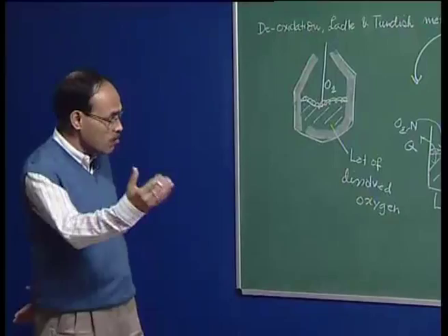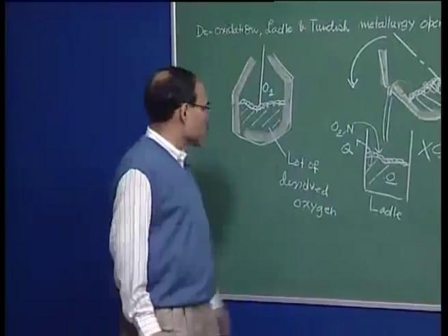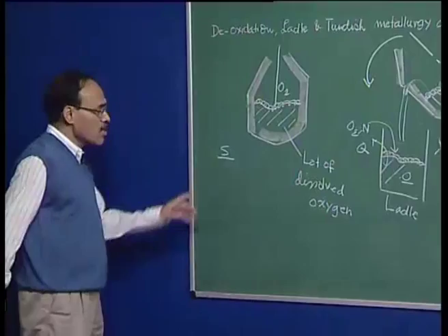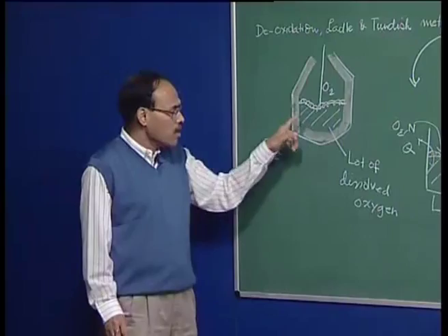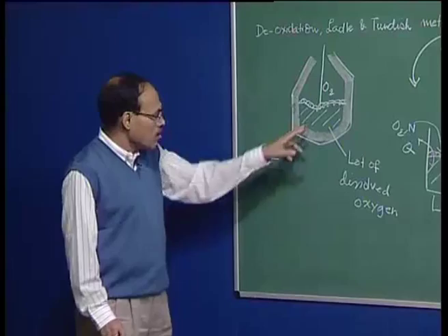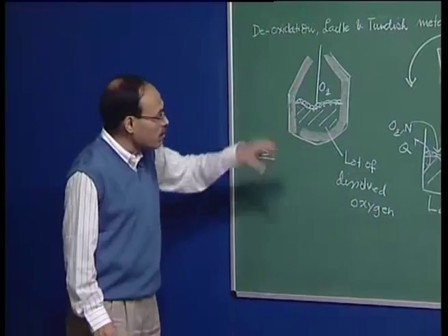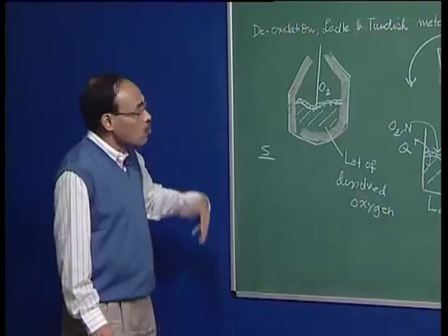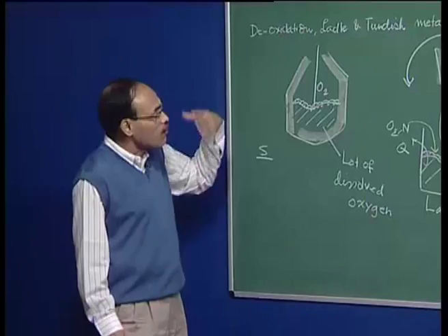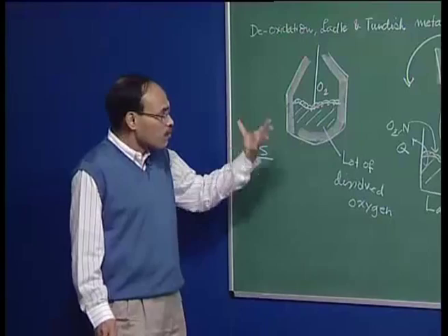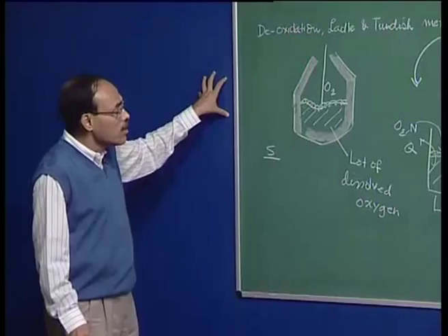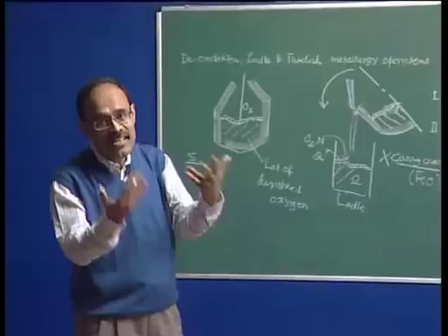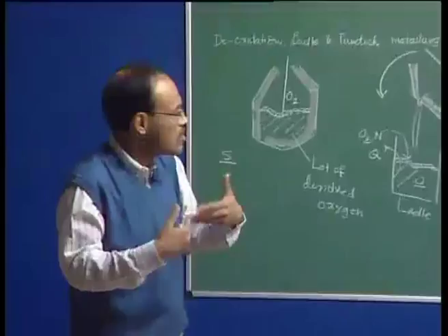right amount of superheat. So, as primary steel making is over, we can assume that there is going to be maybe sulfur, which is more than the required specification, although we would like to have phosphorus absolutely at the right level. I must also mention here that there is an increasing trend that for high phosphorus steel we are going to have some kind of a pretreatment, which you of course have done between blast furnace and primary steel making. We have pretreatments like desiliconization, desulfurization, and we are building up gradually dephosphorization as